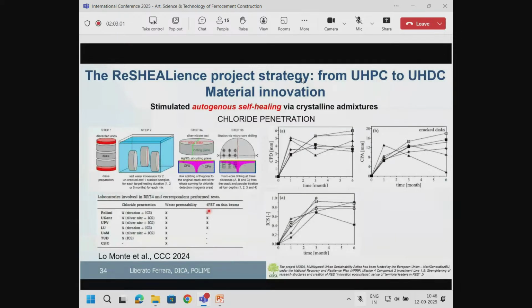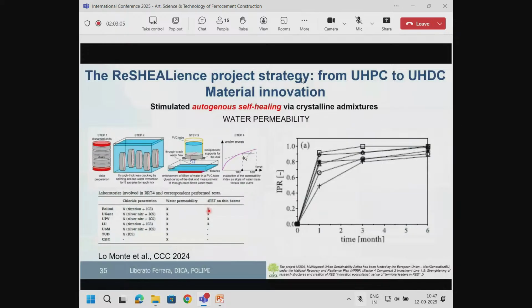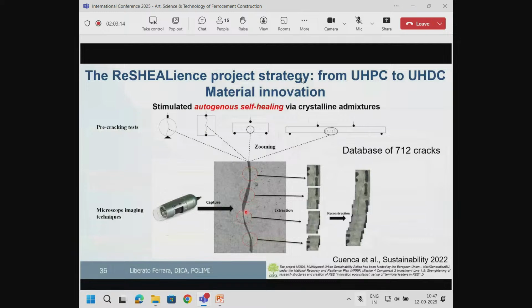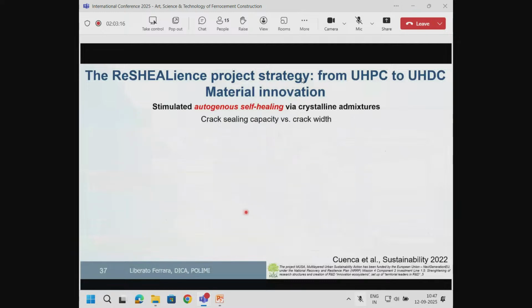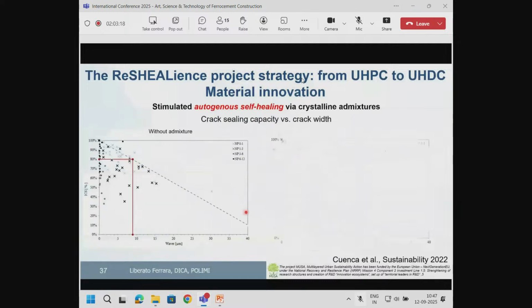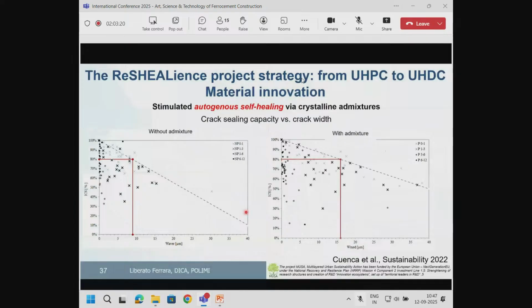So we worked on a round-robin test in order to see whether these results were repeatable, and you can see that with 7 different laboratories, we had a good repeatability of our results. We developed a database in which we collected more than 700 data, and we elaborated them also with the help of